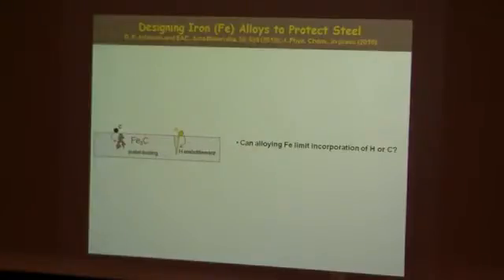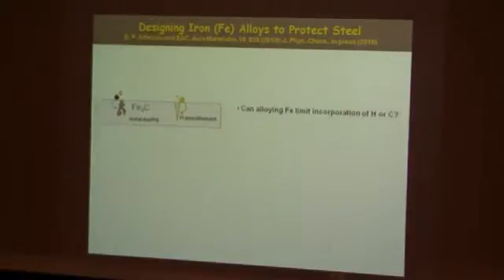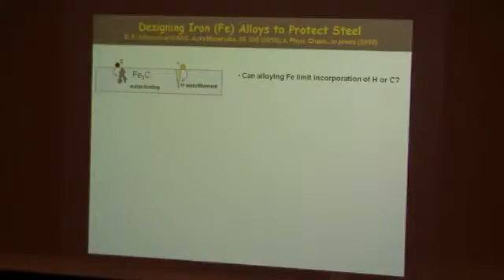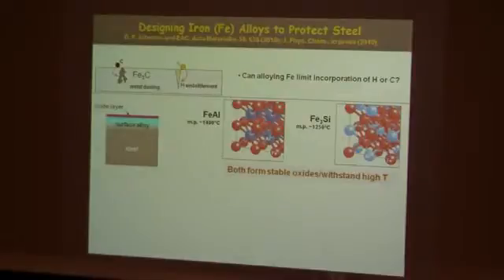And so one question we wanted to answer is, could we design an alloy that would inhibit the hydrogen and carbon from getting in? And so what we did is to, again, look at our friend, the periodic table, and figure out, okay, are there iron alloys that could possibly withstand very high temperatures and that could, in fact, be useful for this purpose? And there were two that were important. It turns out that iron aluminide and iron silicide have very high melting points. They also both form stable oxides on their surface in such a way that they don't corrode. Okay, that's of course very important as well.